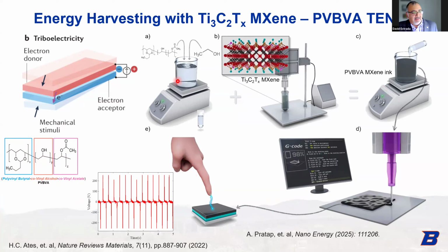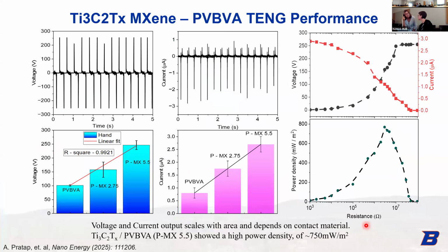So to make this device, we started with just our PVBVA dissolved in ethanol at about 7 weight percent, and then we could add MXenes at different concentrations, just through shear mixing. That creates a thick viscous paste that we can use an extrusion printer for. We just use pneumatic, compressed dry air to push the syringe, and we can print arbitrary shapes. It's a single electrode device where we can print our polymer composite directly on aluminum foil or a printed silver electrode.